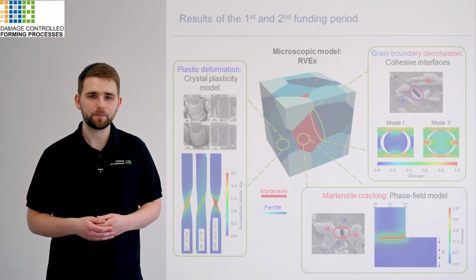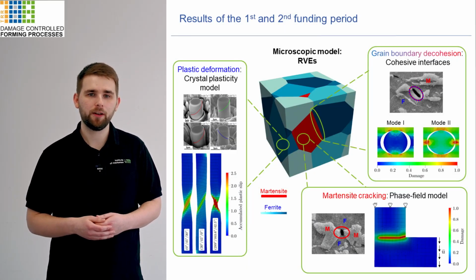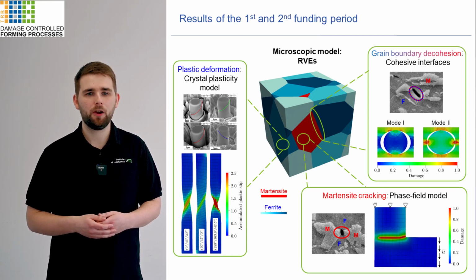In order to account for the underlying crystal structure of the grains, we employ rate-independent and rate-dependent crystal plasticity models. Here, we have to deal with the challenge of non-unique slips on those crystallographic slip systems by means of